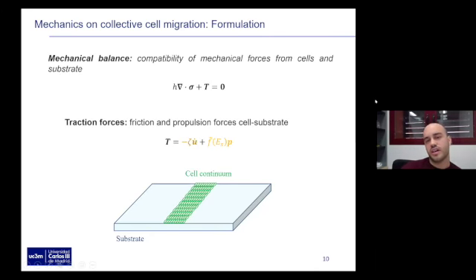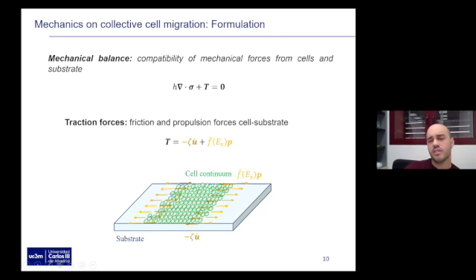So we put together here the internal forces and external forces. We will have this internal cellular stress weighted by the height of the epithelial monolayer. Here sigma is the cellular stress, and T is the traction forces. So we say we're going to have this propulsion force that a priori can be dependent on the stiffness of the substrate, following these previous approaches. And then the direction of that resultant force is going to be determined by this cellular polarization. And then, of course, as soon as we have any system moving on top of the substrate, we're going to have some friction forces, right, opposing that, with this parameter being the friction coefficient.